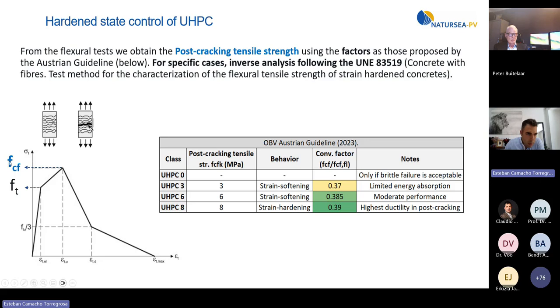I want to clarify what the post-cracking tensile strength is. You can see on the left side that it is the maximum tensile strength of the composite, because it's given by the fibers. Before this is the maximum tensile strength of the matrix, which sometimes is lower and sometimes higher than the post-cracking tensile strength. Depending on this, our material has strain softening or strain hardening.